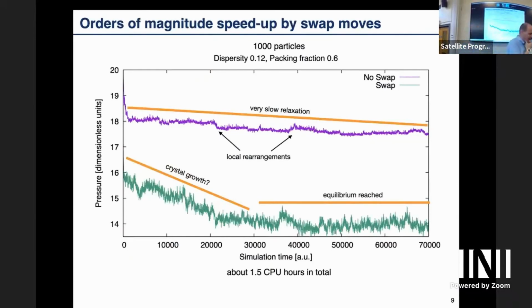And then just to show that, I have this graph here. So what you see here is a comparison of performing simulations with swap, without swap. So this is pressure, and here's time. First of all, this is a relatively short simulation. 70,000 times here with 1,000 particles took me 1.5 hours. Actually, I ran this a few weeks ago on this laptop, and so this is a relatively short simulation. And we use pressure as a means of analyzing the progress of the simulation.